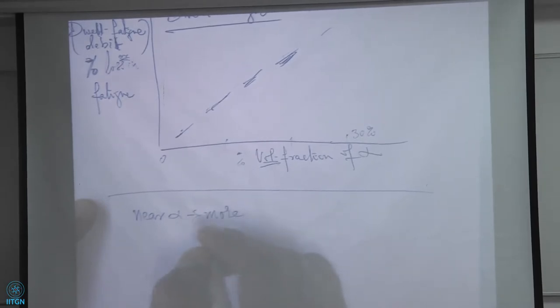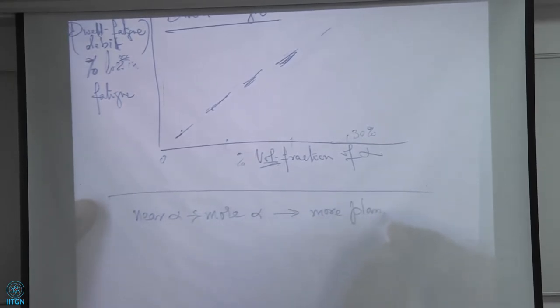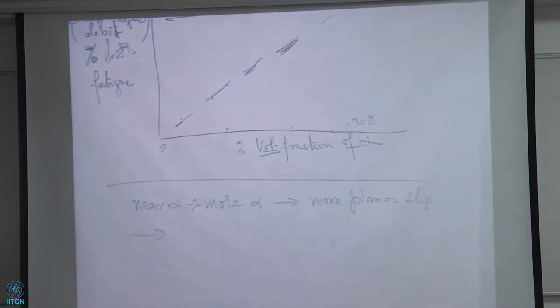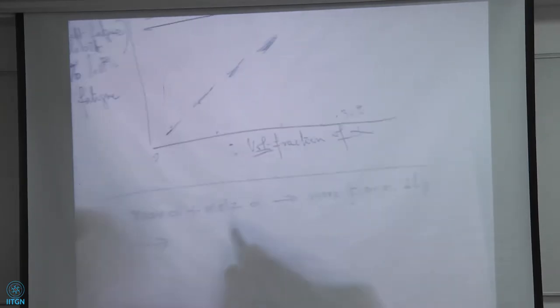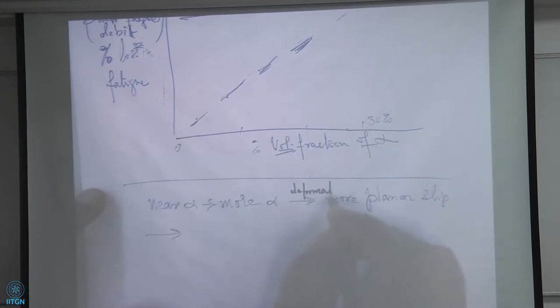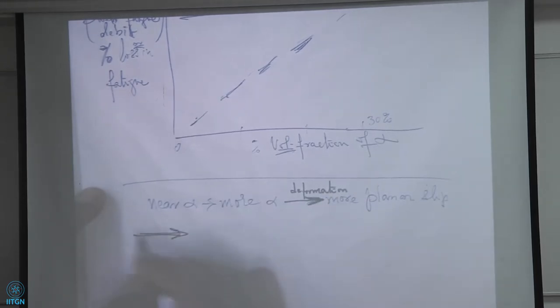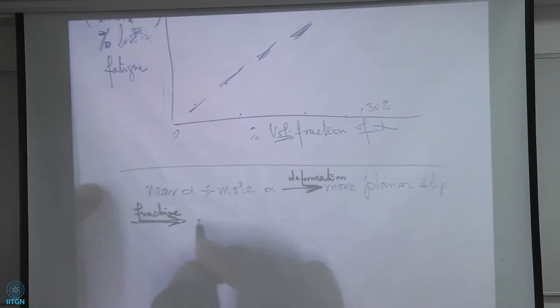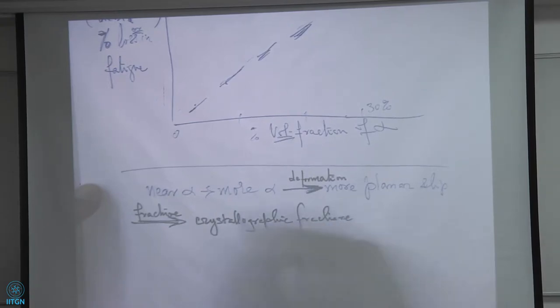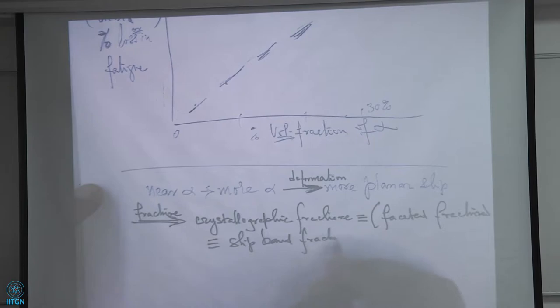And it's an old problem. It's a 40-year-old problem where we find that it happens at low temperatures, like 120 degrees C, and for titanium, 120 degrees C is not very much, as we just said. And then it happens in the cold part of the engine, so that's like the fan. And it's a serious problem because the NDE inspections have to be done more often, and the designers have to overdesign so that nothing breaks. So we design more on the safe side, so the engine can become heavier.